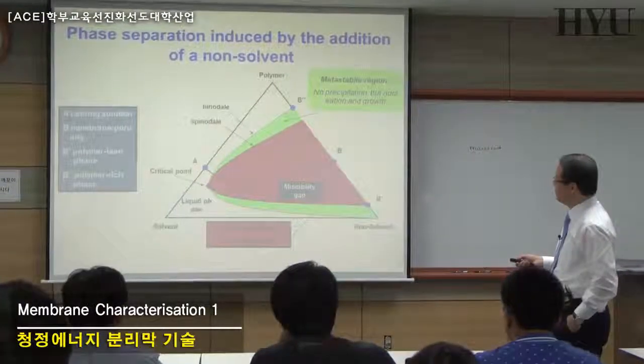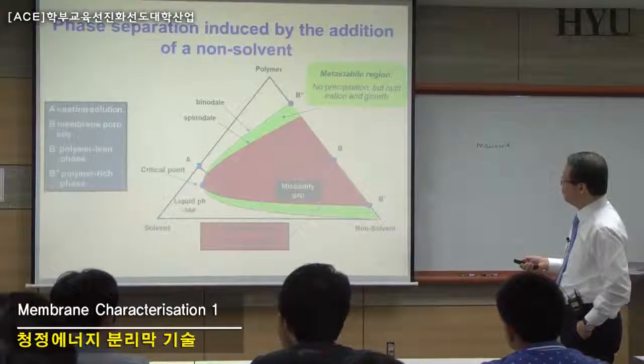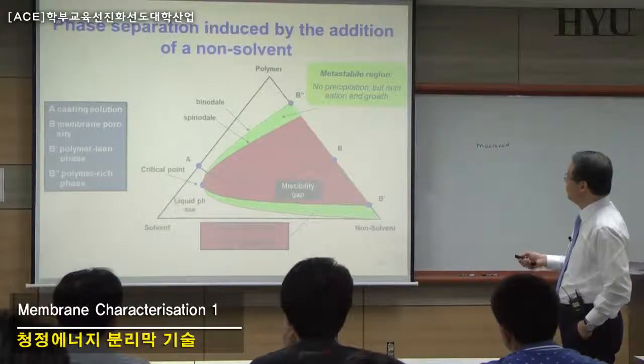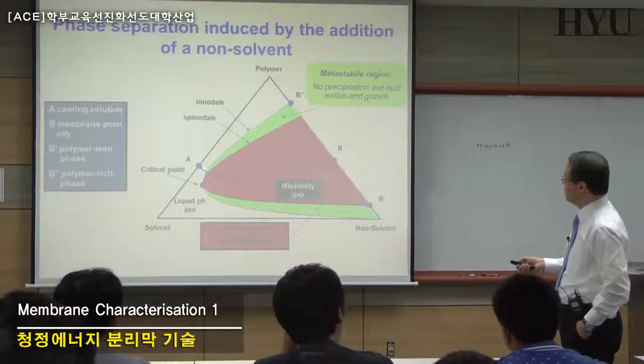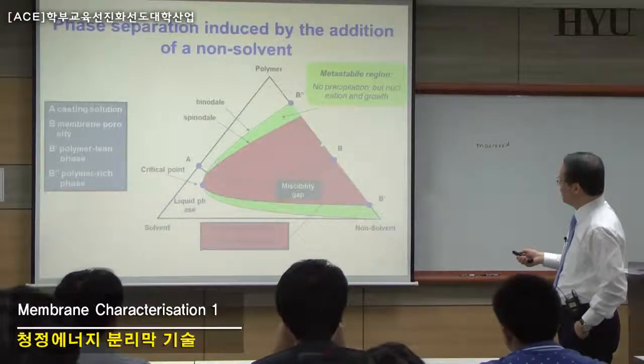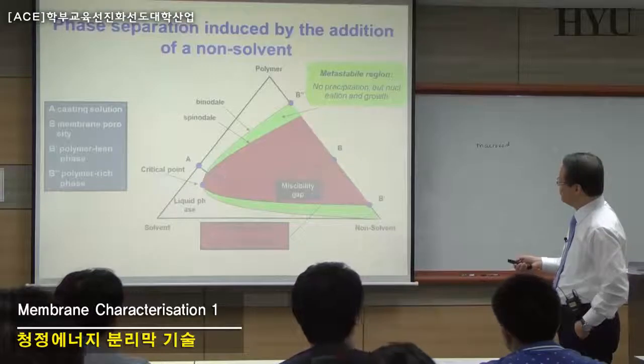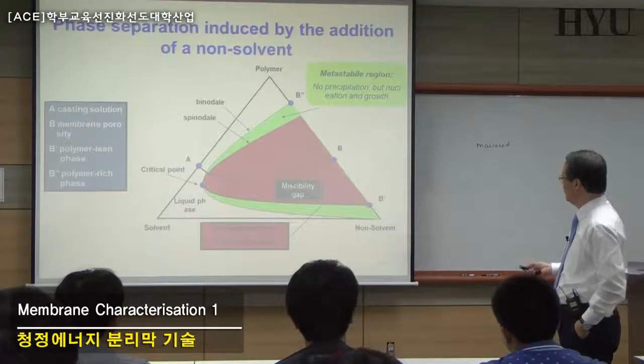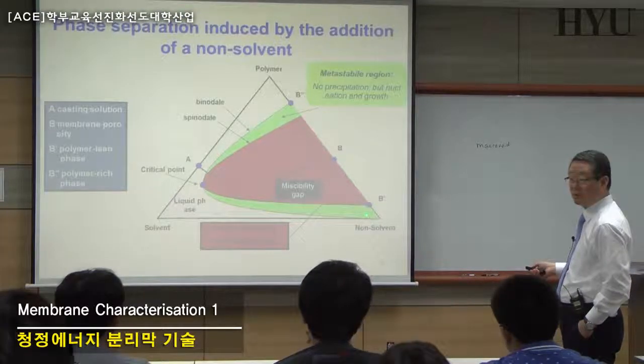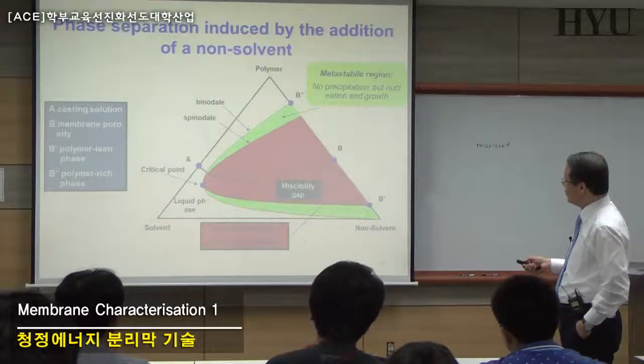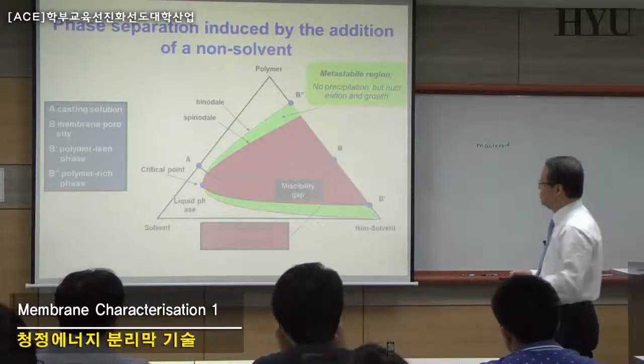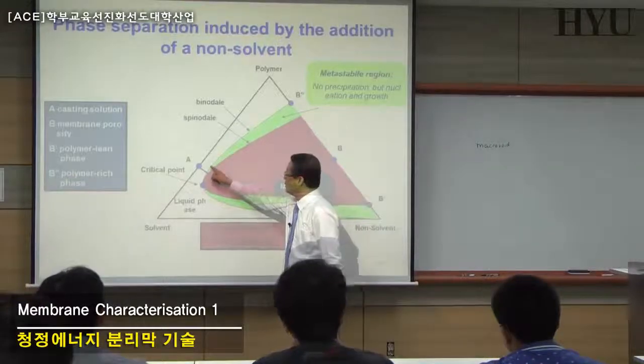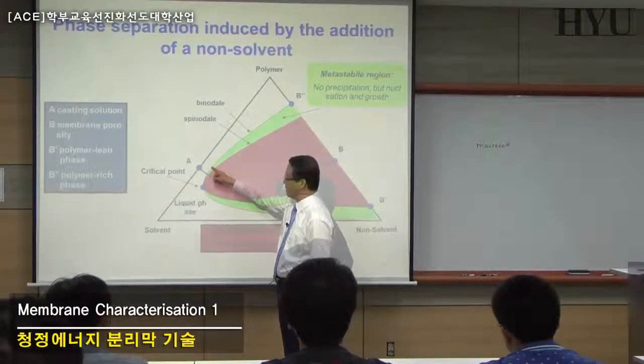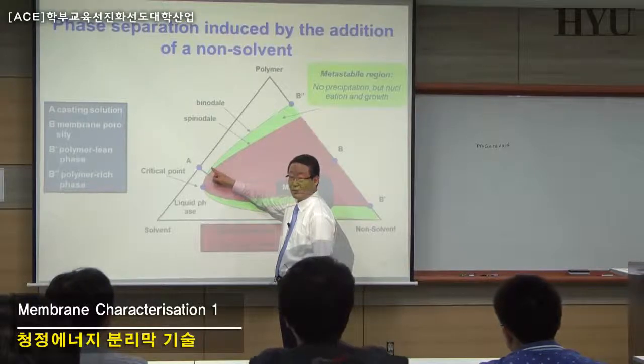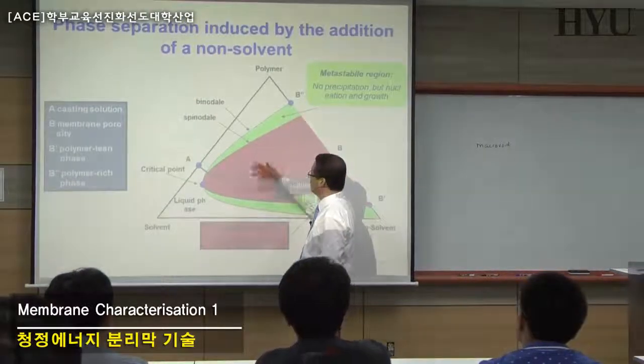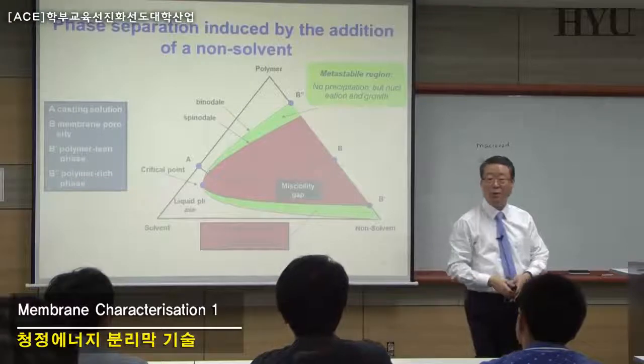So, for example, if I have an A point here, A point means I have a polymer, maybe about 30% of my polymer. I may have about 70% of my solvent, and I have 0% non-solvent. I did not put any non-solvent here at this point, but if I move the A point to here, that means I may have maybe about 5% non-solvent. Okay? So any point can be described by the composition of those three components.